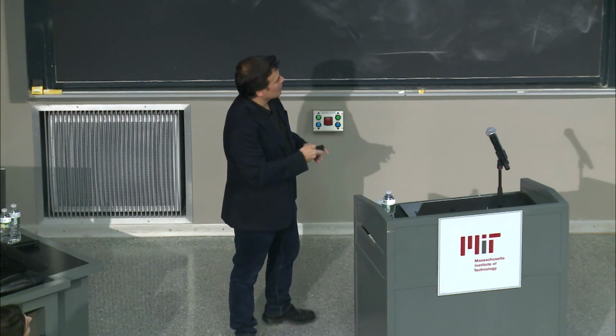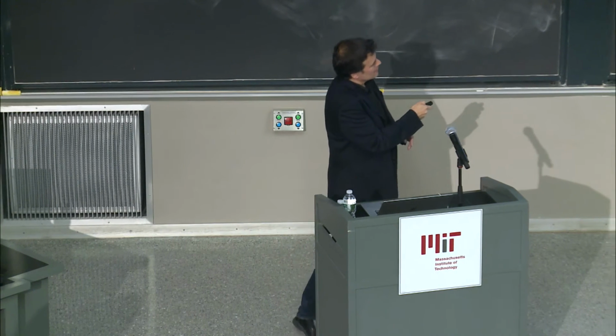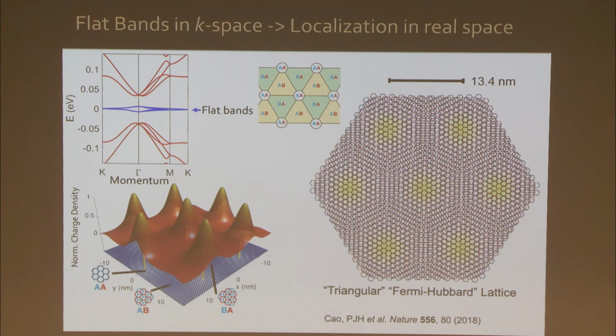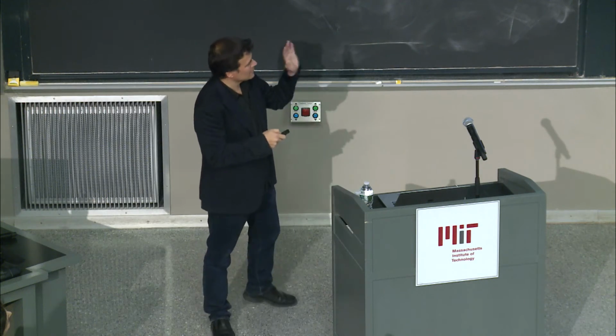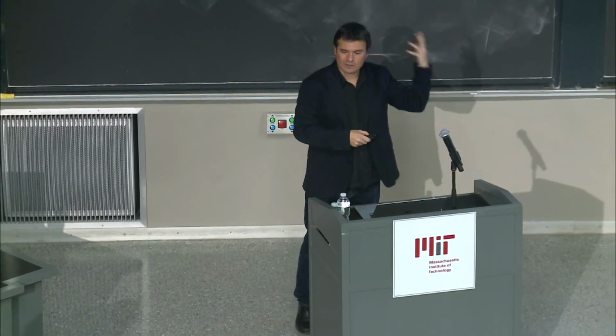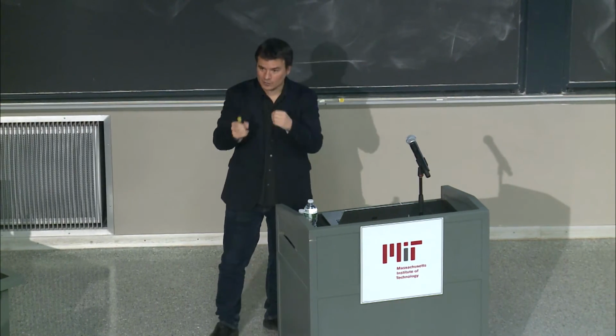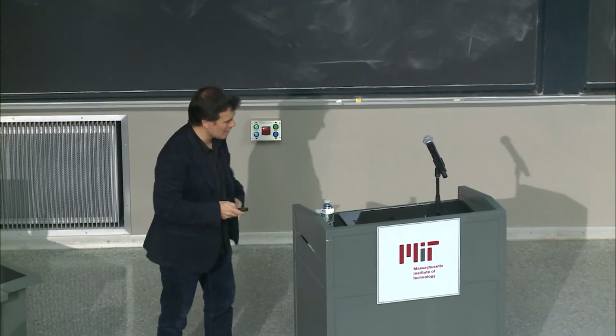Now, I put many quotes here. First of all, it looks triangular, but it's not triangular. The AB and BA regions are not identical, so it's actually a honeycomb lattice also. And I put Fermi-Hubbard lattice in quotes because it turns out the electronic properties of these flat bands have interesting topological characteristics that prevent a direct mapping to those ultra-cold atom lattices. The wave functions have very different character. But you can think of it as a lattice where we're going to put electrons and see what happens.